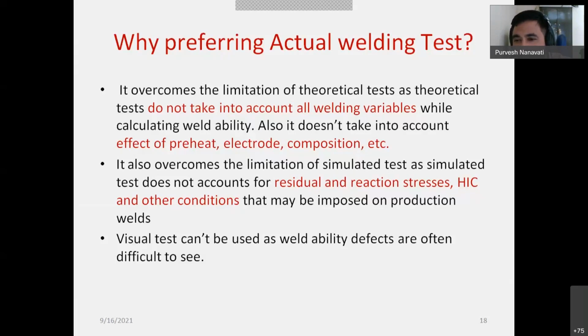So as a result, what will happen? Some residual stresses remain on the weld joint. Most of the time, tensile residual stresses are present on the weld joint. These residual stresses, if they are not relieved by means of post-weld heat treatment or by any thermal means, right? There are various methods of relieving the residual stresses, and also of measuring residual stress.